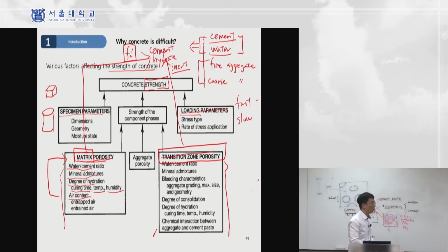among all of these lists, the most dominant factor to affect the material properties of concrete materials is the property of this region. Okay? This region is called the transition zone. Transition zone. Okay. So this transition zone is actually the space or the region between the cement paste and the coarse aggregate. Okay. So that transition zone parameter we can see is here. Okay. So transition zone porosity is the most dominant factor to determine the material properties of this composite material of concrete. So why? I will explain later.